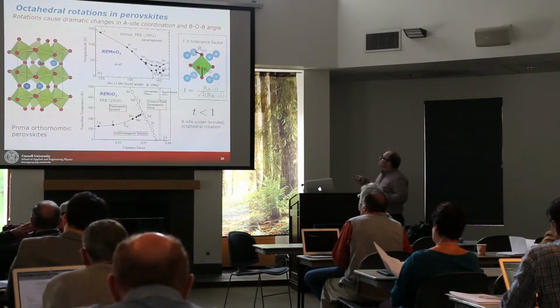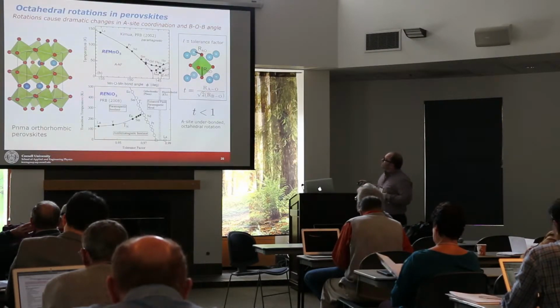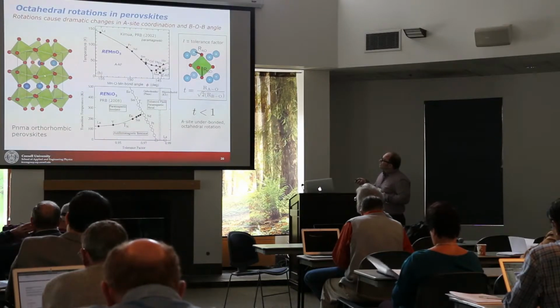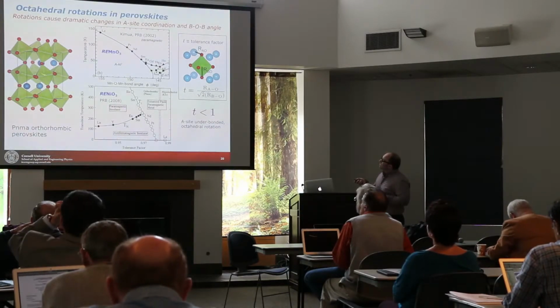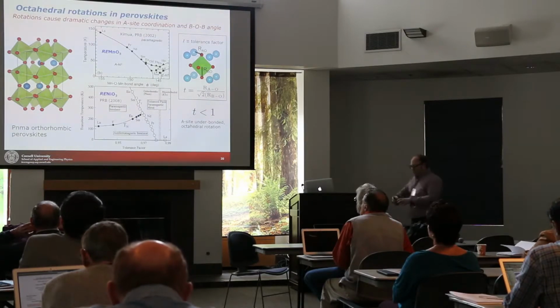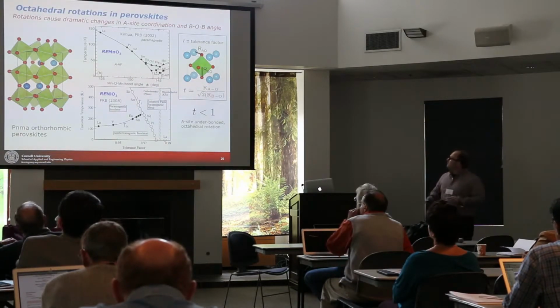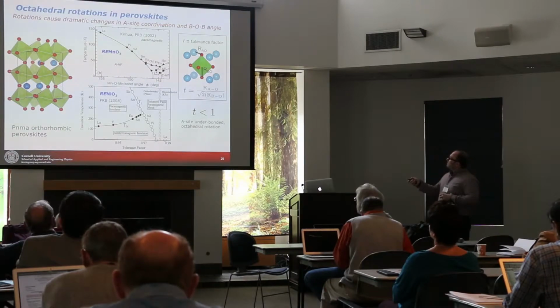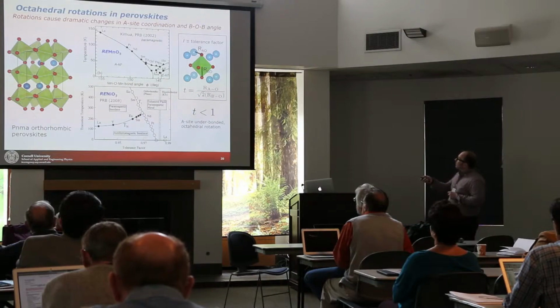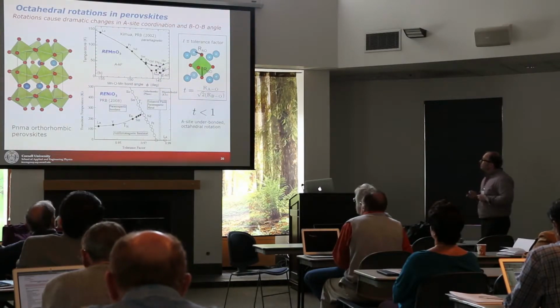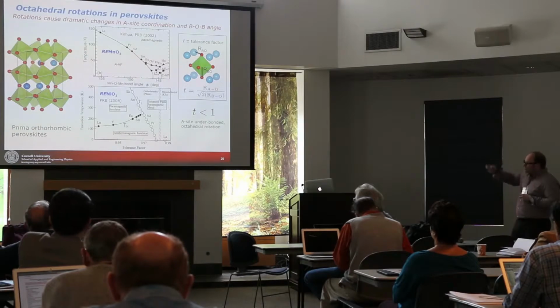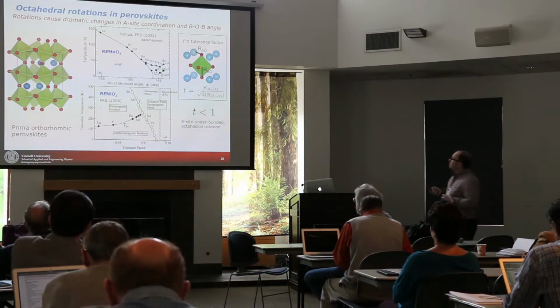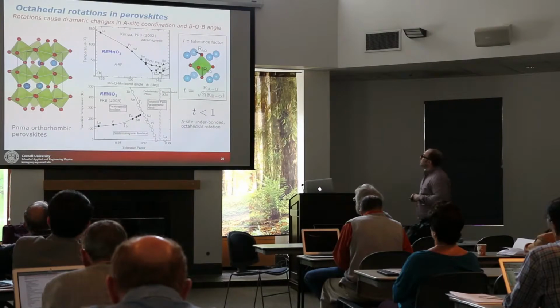We're not adding or taking away electrons, simply changing the size of the cation on the A site. And what I'm showing you over here is the manganese-oxygen-manganese bond angle for this top graph. So that is the angle between the atoms here, let's say the manganese atom here, the oxygen and manganese. If this was a cubic structure, this would be 180 degrees. As we make the cation on the A site smaller, this rotation increases. As you can see here, if we make the cation smaller, the deviation from 180 degrees increases more and more. Rotations become larger.